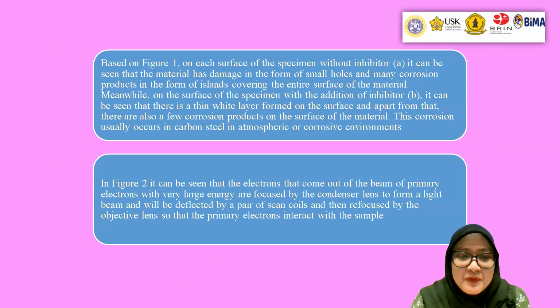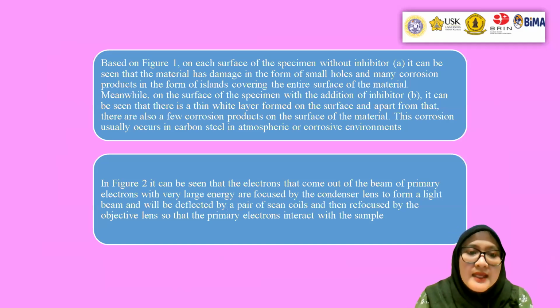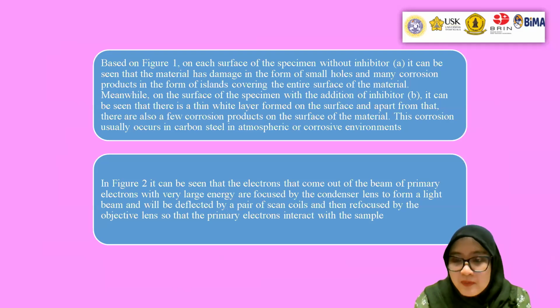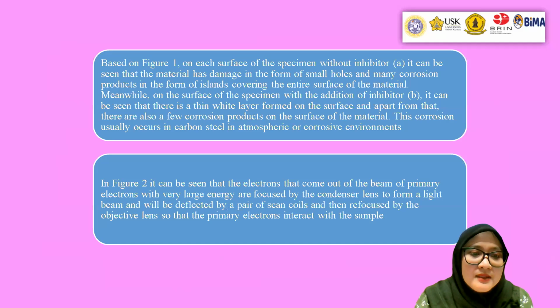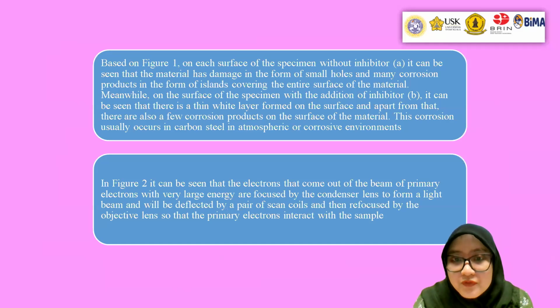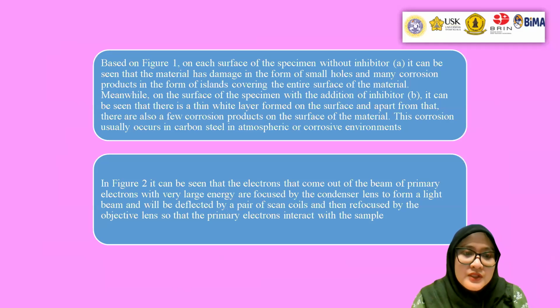covering the entire surface of the material. And meanwhile, on the surface of the specimen with the addition of inhibitor, it can be seen that a thin white layer formed on the surface, and apart from that, there are also a few corrosion products on the surface of the material, and this corrosion usually occurs in carbon steel in atmospheric or corrosive environments. And in figure 2, it can be seen that electrons that come out as the primary electron beam with very large energy are focused by the condenser lens and form a light beam and will be deflected by a pair of scan coils and then refocused by the objective.